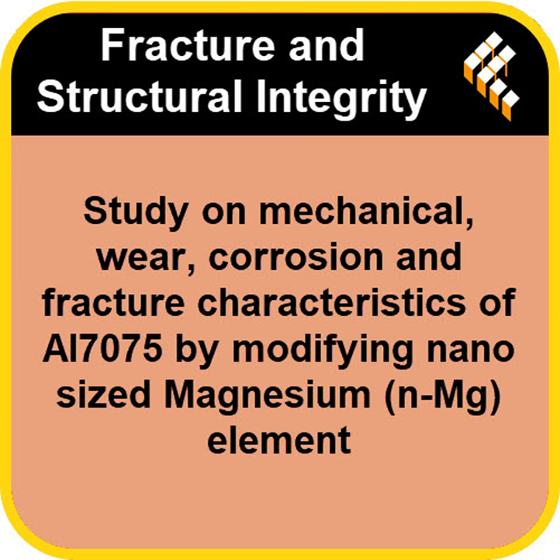Magnesium behaves anodically compared to aluminum. Okay, break that down for us. To put it in simple terms, the magnesium acts like a sacrificial battery, or maybe a fuse wire, inside the aluminum structure. It's just chemically more reactive. So when its concentration goes up, that increased reactivity means it will break down first. And in doing so, it rapidly speeds up the destruction of the alloy's natural protective layer. Which is the aluminum oxide coating. The Al2O3 coating, exactly. So the magnesium is sacrificing itself, but in doing so, it creates all these weaknesses across the entire surface.